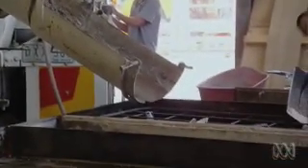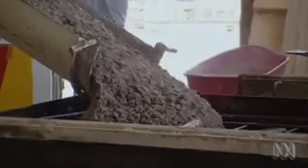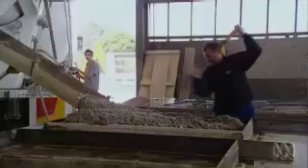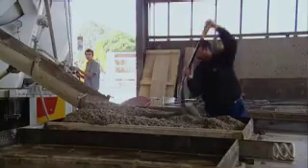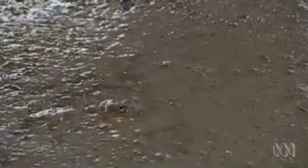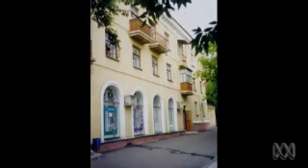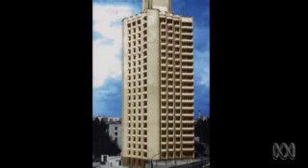But it's all very well having a cement with a low carbon footprint. Is it any good? For example, will it do what ordinary cement does year in and year out? Well, it turns out a similar type of cement was developed in the Soviet Union in the 1950s and 60s. What we have is that the Ukrainians have developed a concrete based on alkali activation, so the same type of chemistry as we use, but they've used only slag, not fly ash. So those old slag structures that are based on the same chemistry have been standing there for 45 years.